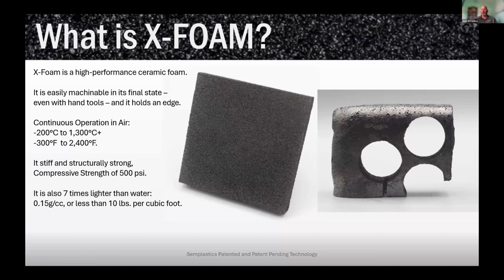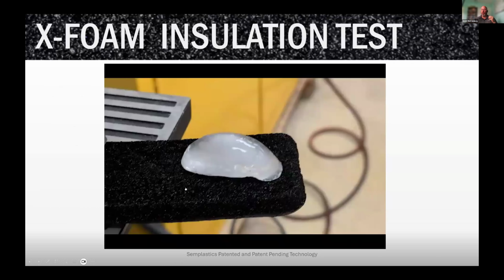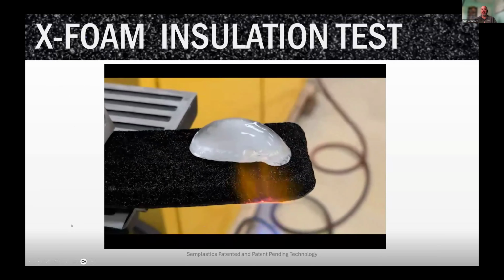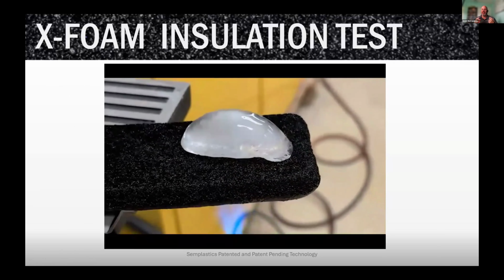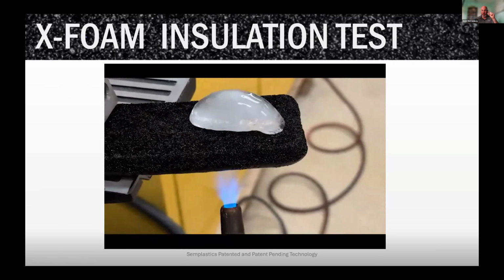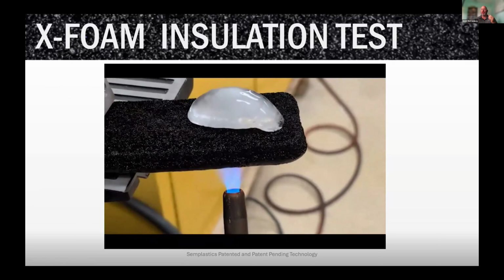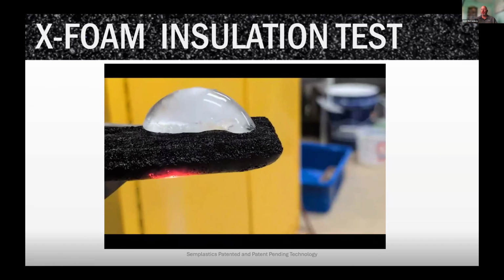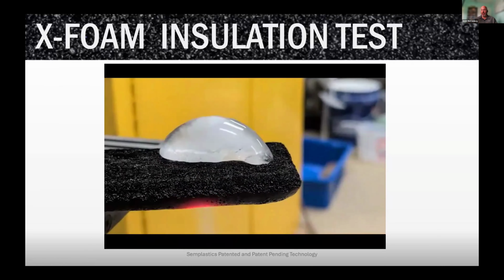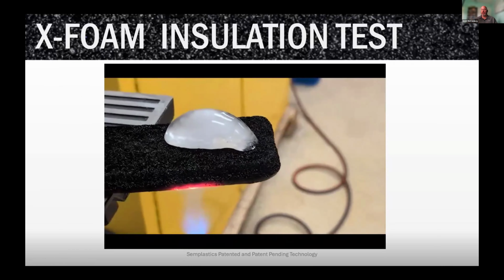What's really special about it also is that it is stable in air from cryo up to 1300 and in some cases 1400 degrees centigrade, which is up to 2400 or 2500 degrees Fahrenheit. So it is a very wide range of temperatures that it's good for. It's also 7 times lighter than water. One of the most spectacular things about it that we're very excited we discovered is that this little slab of about a little less than 1 centimeter, about 3/8 of an inch, of this X-Foam is able to keep this ice from melting, even though it's being hit from the bottom by a 2000 C propane blowtorch, and the ice does not melt.